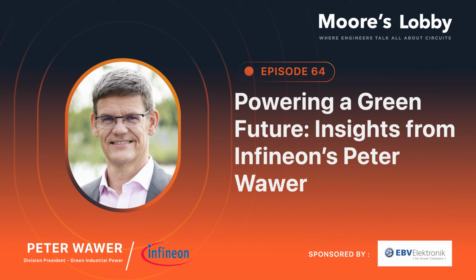Absolutely. Okay. Interesting. If you like, a short comment also on the gallium nitride topic. Absolutely. The interesting thing is that with silicon, from the silicon MOSFET, you go from a couple of volts blocking voltage up to 6,500 volts, which is in our case the highest blocking voltage, which we achieve then with IGBTs. So basically on the same material, but of course different technologies, MOSFETs, IGBTs, you can cover the full range of voltages which are used in the industry of power semiconductors.